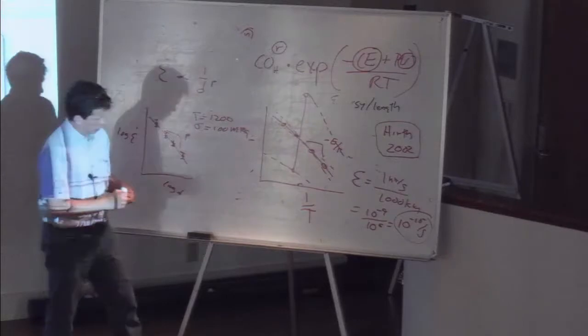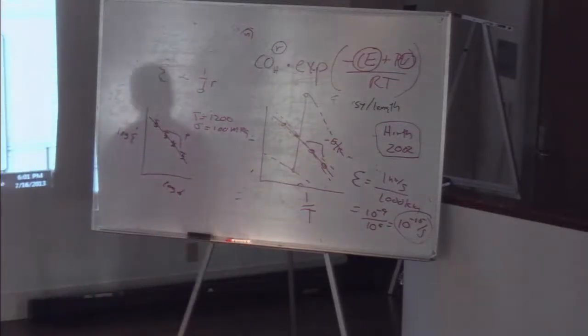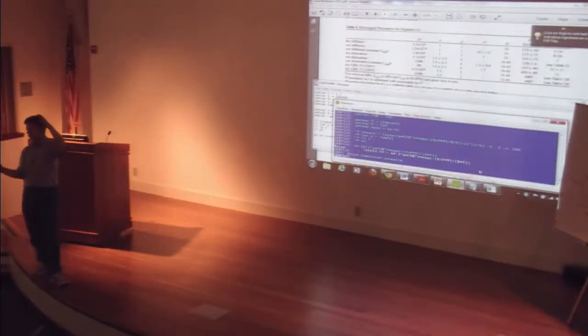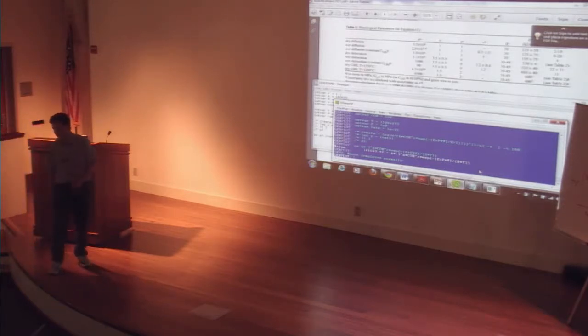So is that the difference between like grain boundary and... Yes. Remember yesterday I talked about the diffusion gradient. So one of the grain size dependencies is from that. The other is from taking a displacement rate and turning it into a strain rate. So that's the displacement rate divided by the grain size. And then the last one is related to the grain boundary diffusion. If it's grain boundary diffusion, you have a grain boundary width divided by grain size term. So you end up with d cubed. So then these are technically experimentally determined. Yes, these are all experimentally determined.